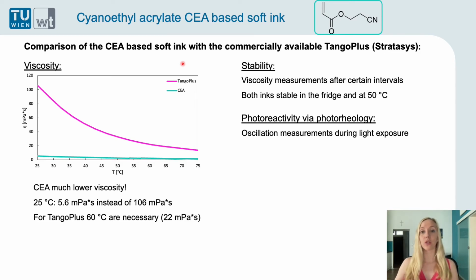Furthermore, I investigated the photoreactivity via photorheology measurements. These are oscillation measurements during light exposure, and in this way you can record the storage modulus and the loss modulus, as well as the double bond conversion over time. And here you get a lot of parameters which can be compared, and I will show you two important parameters